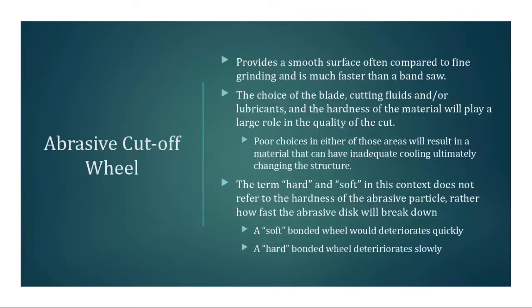Then when you look at the abrasive cutoff wheels, this already provides you a smooth surface, a much smaller mechanical damage layer, and really the choice of the blade, the cutting fluids and or lubricants, and hardness of the material are going to play a large role on the quality of the cut that is performed. Okay, if you're cutting a very hard material with the wrong blade, then you can actually mechanically deform the material, creating a harder surface to cut.